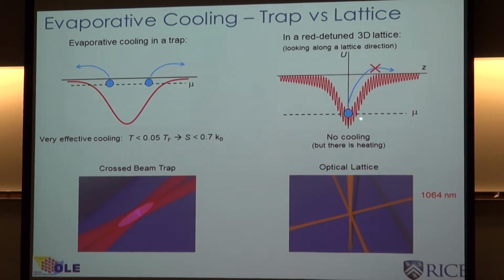In a lattice, the chemical potential sits way down in here. This is the confining envelope of the lattice. This is the lattice sites. The scales are, of course, changed here for illustrative purposes. But you can see that the Maxwell-Boltzmann factor for an atom to escape from the lattice is almost zero. There's almost no evaporation that can happen. And so this is a typical lattice situation.